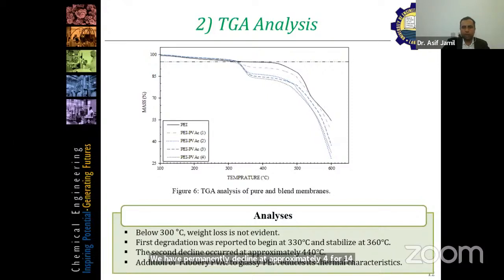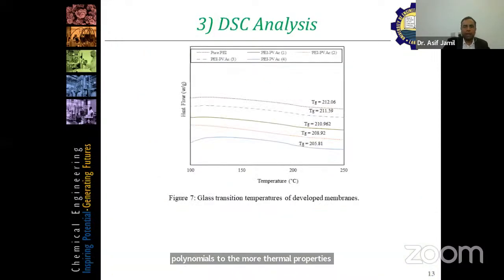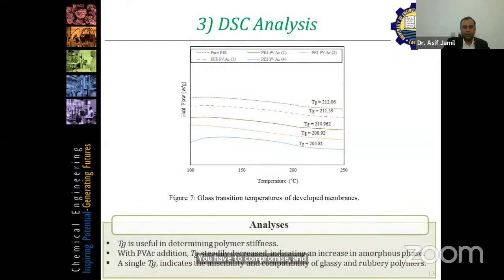For example, if we look at the black line, which shows pure polyetherimide membranes, its thermal properties are higher compared to when we add polyvinyl acetate. So the more you add polyvinyl acetate, the more thermal properties you have to compromise. And the other thing is DSC analysis, which is very important, especially when you are dealing with blend polymers, since we want to know whether it's miscible or not miscible.